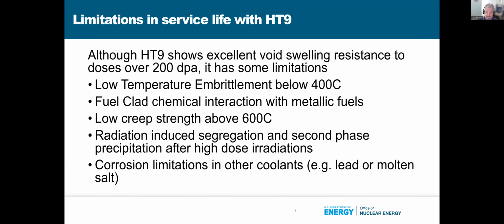The first one, of course, was what I pointed out clearly here, which is low temperature embrittlement below 400 degrees C. There are some better ferritic martensitic steels that don't show as much low temperature embrittlement, but still even below 350, these materials do show some low temperature embrittlement. Fuel clad chemical interaction. I didn't go into this, but for high dose or high burnup irradiations with HT9, you do start to get interaction between a metallic fuel and the cladding. So that's something we would have to either put in a coating or a new material to avoid.